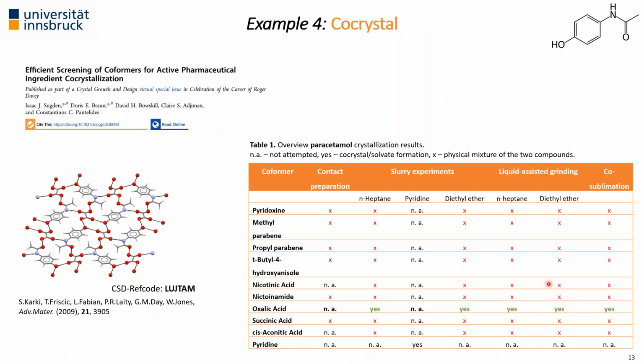And the last example, sorry for quickly jumping to another topic, was using co-sublimation as a co-crystallization technique. Because when we want to produce co-crystals, which are composed of two compounds within the crystal lattice, as exemplarily shown here for paracetamol and oxalic acid. And this table is taken from one of our most recent work, together with the group at Imperial College in London. They did computational screenings for polymorphs. We in Innsbruck here did the experimental work, contrasted it. And for the paracetamol system, there is one co-crystal, which was already known prior we started the work, the oxalic acid. We could reproduce it using the standard techniques, but also this co-sublimation technique.